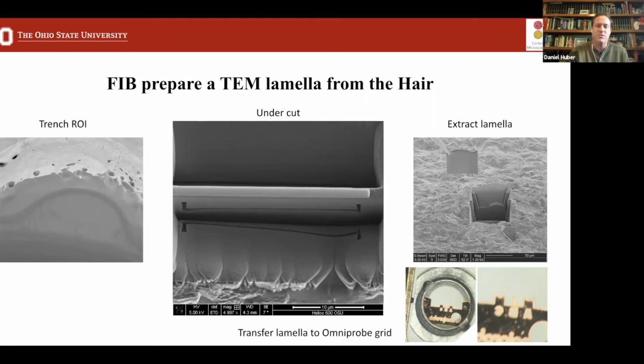So I don't have very many pictures from the lift out of this particular bubble. But what I'm going to include here is a couple of example images from some specimens that were produced from regular materials or hard materials. First, we're going to trench on either side of that bubble, and we're going to cap the area with a little bit of platinum.